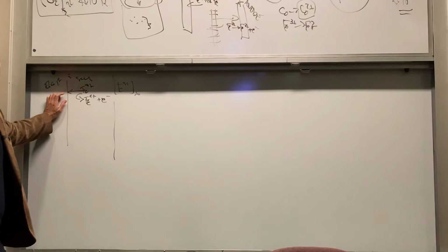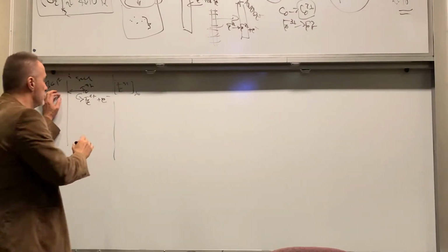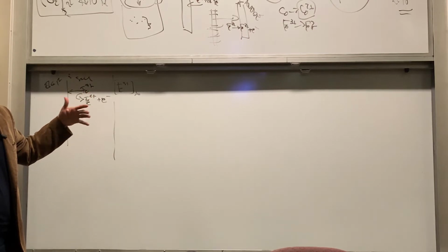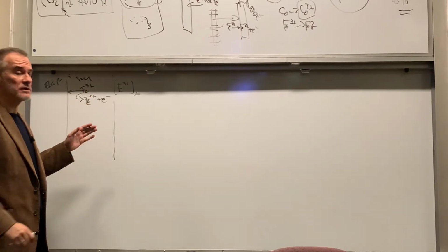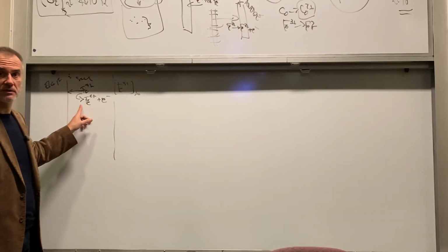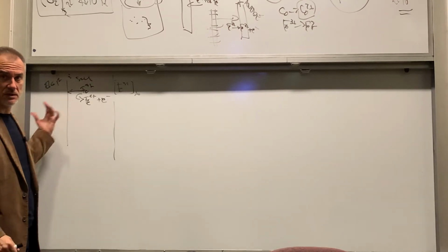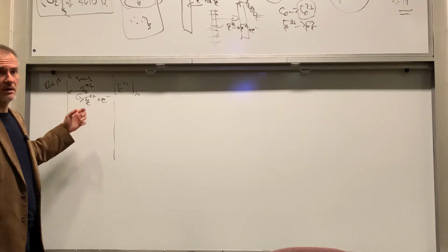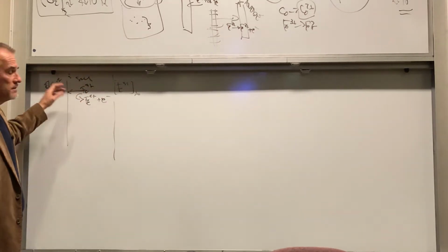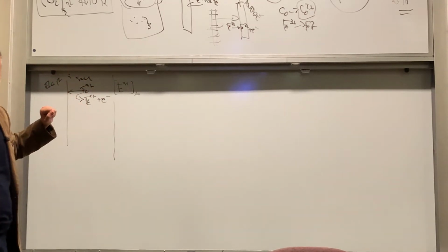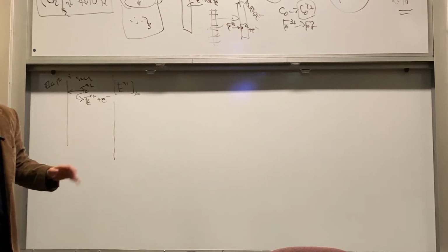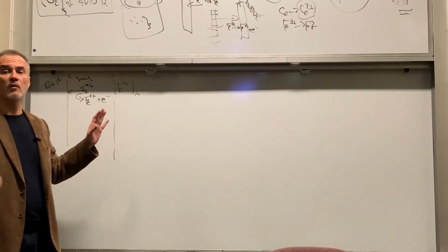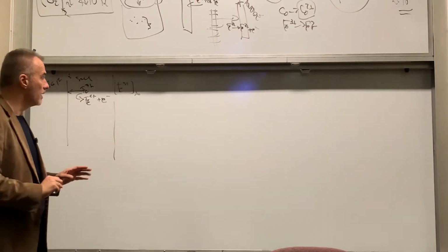the interfacial iron 3 plus should be to some extent smaller, because it's reasonable to expect that there will be some reduction of iron 3 plus to iron 2 plus. It's a negative potential. The equilibrium potential of iron 2, iron 3 is way more positive, so if you're on the negative side, you should expect this to happen. Everybody understand this? So part of iron 3 is converted to iron 2 during electrodeposition.